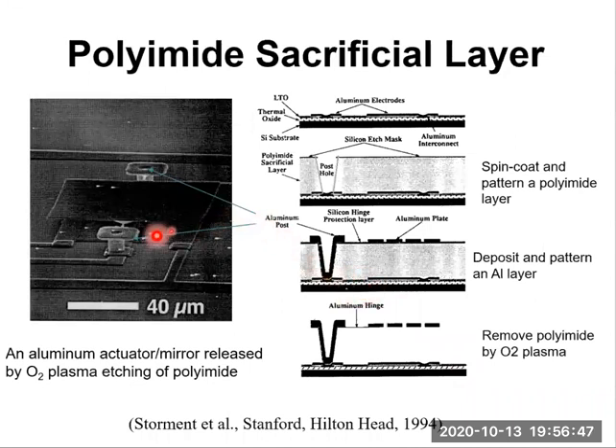Now let's take a look at an example which uses polyimide sacrificial layer. This SEM image shows an aluminum actuator or mirror. So this structure is an aluminum mirror, released by oxygen plasma etching of polymer. We know that this mirror or actuator is freestanding. So there is a polymer underneath, which is removed by oxygen plasma.